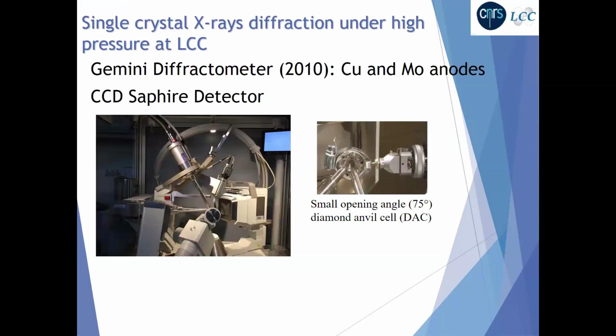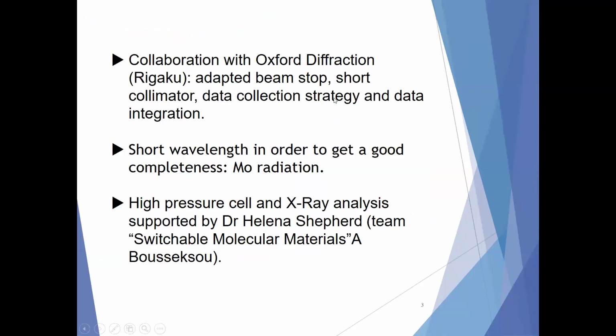Concerning the history of high pressure studies in our laboratory, everything began in 2010 with the acquisition of a Gemini diffractometer. So from Oxford Diffraction, which is now Rigaku. This diffractometer was equipped with two standard X-ray tube, copper and molybdenum, and with a CCD sapphire detector. We had already a DAC, which was actually with a very small opening angle, only 75 degrees. Thanks to a first collaboration with Oxford Diffraction, we got, with the Gemini, a high-pressure setup.